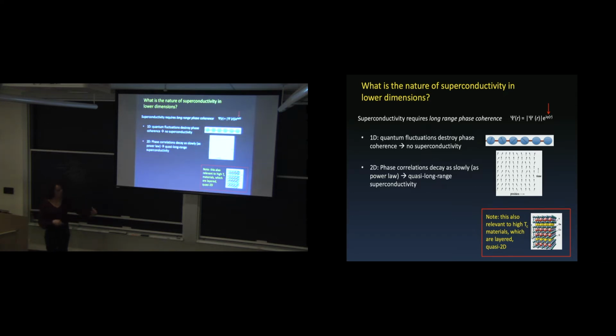Okay, so a single fluctuation in a 1D system will destroy phase coherence, so you should not have true long-range superconductivity in a real 1D system. Okay, then what about 2D? It turns out that 2D is the lower limit for superconductivity. You can have phase fluctuations, but they die out as power laws. And so you should have not true long-range order in 2D, but long-range order that decays as a power law. So you can see superconductivity, just not over infinite scales in a 2D system.